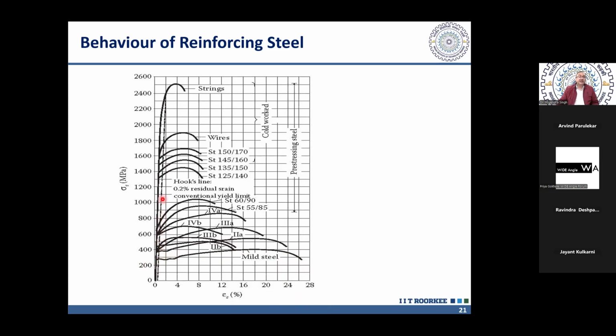Now, strength of steel can be enhanced using different techniques which require change in chemical composition, then cold working or thermomechanical treatment, the TMT. Nowadays, you are hearing about Fe500 and Fe550. So these are the steels, Fe500 and Fe550, and Fe415. So you can see that the strength can increase here, but the ductility reduces. So ductility here is roughly 14%. And our code IS 13920 says that any steel which is having total elongation less than 14.5% cannot be used. So minimum 14.5% ductility or ultimate strain in the steel we should have to use in the seismic area. Then only we can achieve ductility in the member.